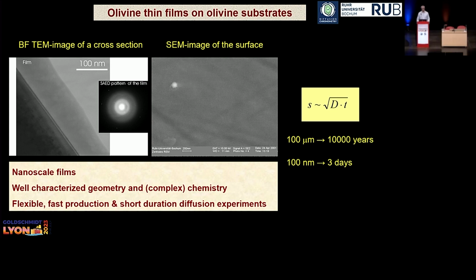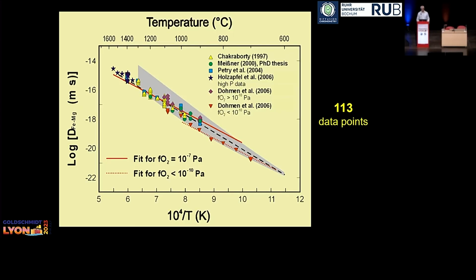So with that, what you can do is, because diffusion scales as a square root of time, if you have a natural process that happens at 10,000 years and gives you a profile of 100 micrometers, you can actually do the exact same experiments, same conditions, in the lab for 3 days and get 100 nanometer profiles and study that. You don't have to extrapolate. And that meant that we could collect a lot more diffusion data. This is iron magnesium diffusing in olivine as one example.